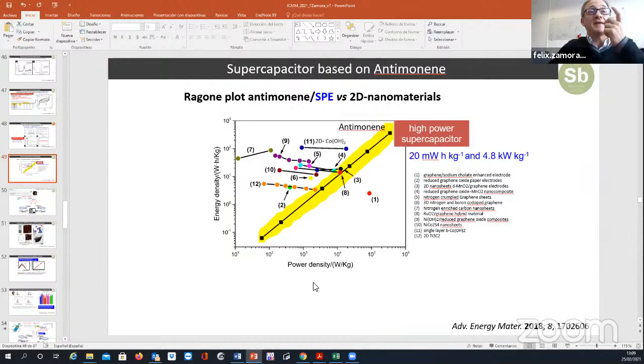of material. Now we hope that using the antimony that we can produce bottom up by chemistry, we can end up with a real supercapacitor and determine properly the power density and energy density of the real capacitor. But as you said, here we plot these values, playing with the amount of antimony, and here we have two exceptional values.